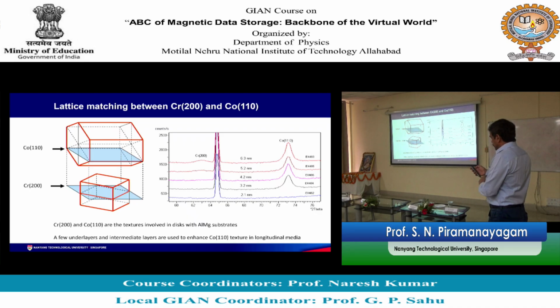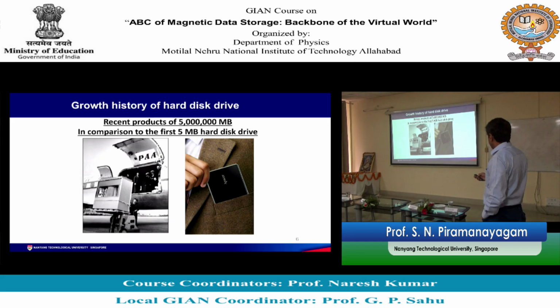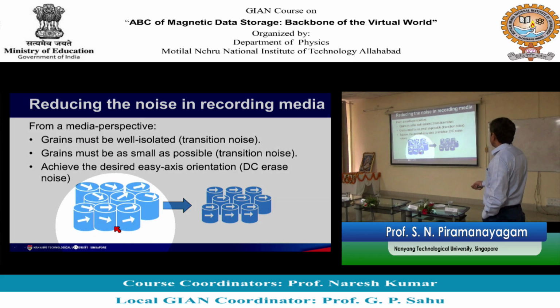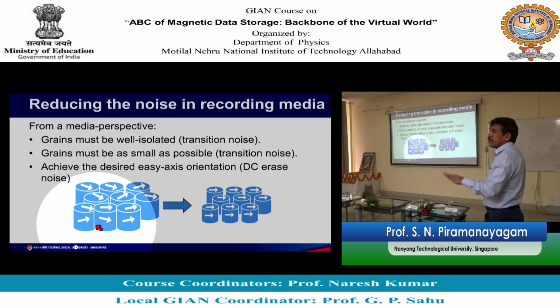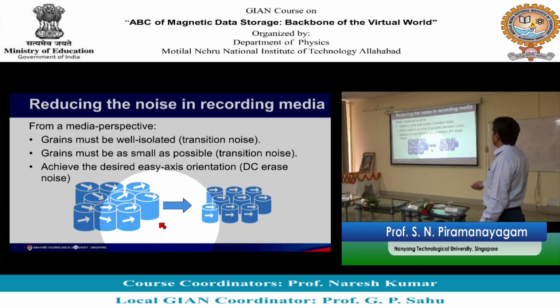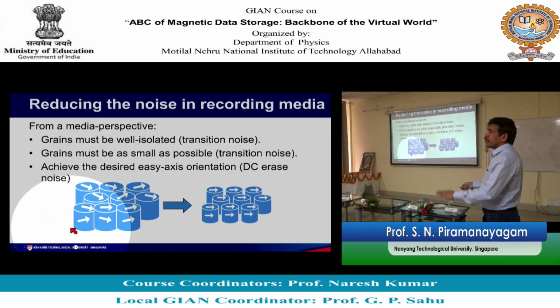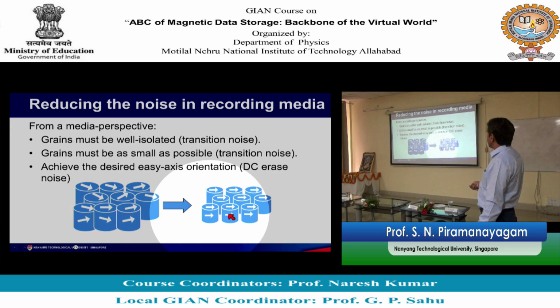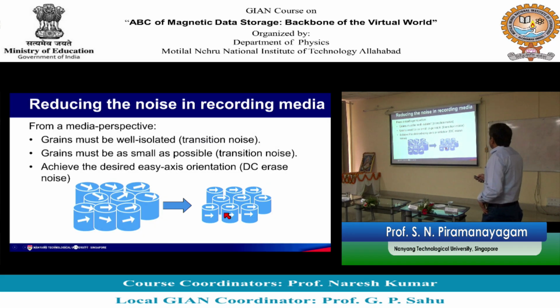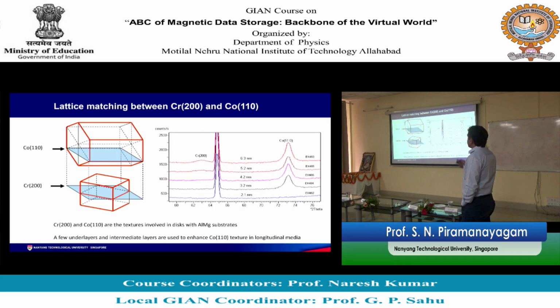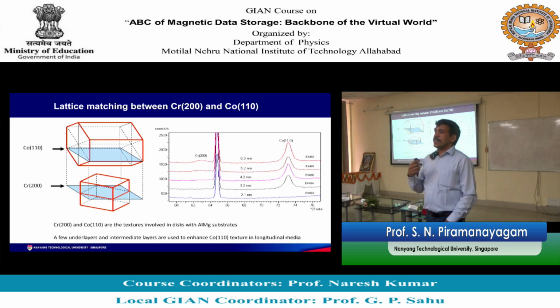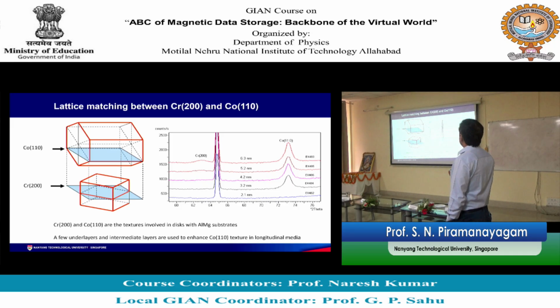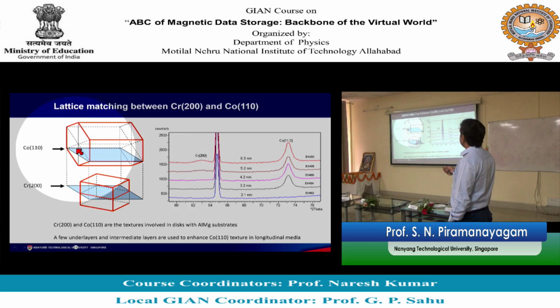So typically, how people try to minimize the magnetization from pointing away from the plane. We do not want this kind of out-of-plane magnetization for in-plane magnetic recording, so we want to make them as parallel as possible. To achieve that, people will use some underlayer. Just a magnetic layer is not enough. You want to force the magnetization to be parallel to the substrate, so people will use underlayers like chromium.